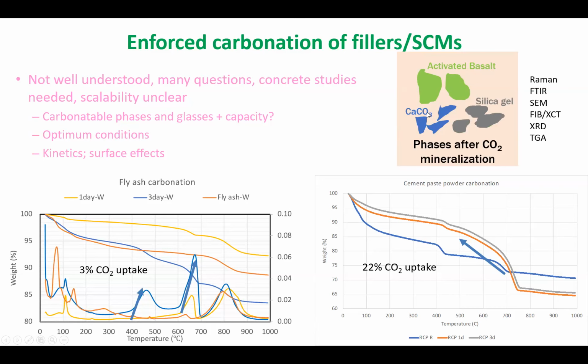The major challenge is this. So we know what the carbonatable phases are. You can put together a list of all the phases in cement and concrete that are carbonatable. But there's a lot of evidence that for the phases, we sometimes only get 20% of the theoretical; in some it's a little higher, in some it's a little lower. So we actually don't carbonate anywhere near the full capacity. Why is that? That's a big question. Then the calcium aluminosilicate glasses, the synthetic glasses, which are a model system, nobody has studied those glasses for their carbonation. And that's actually very interesting because they are fundamentally simple model systems to explain what's happening.